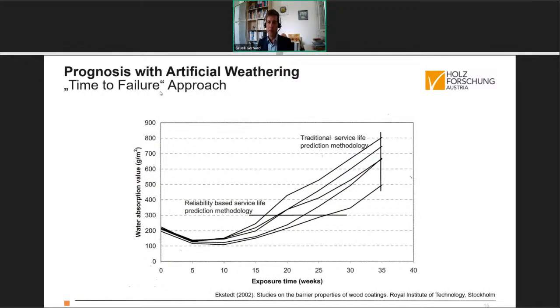We have chosen a nice approach for this, the so-called time to failure approach, where we look for the time until a certain limit stage is reached. And I took this picture of the dissertation of the PhD thesis of Jan Ekstedt. He did some similar things on service life prediction with water absorption tests, but the principle is shown here very nicely. We look for the time it needs until a certain limit stage is reached, whereas traditional weathering tests look at the samples after 1 year, 2 years, 3 years weathering. We look how long does it take until the coating is degraded and has reached a certain limit stage.